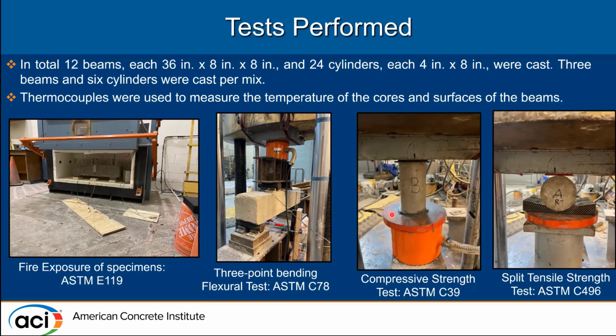Since we were to fire expose these specimens, we used thermocouples to study the surface temperature of the beams and cylinders. The tests performed on these specimens, starting with the slump flow test, that's ASTM C1611, and then the fire exposure of specimens as per ASTM E119, 3-point bending flexural test as per ASTM C78, compression strength as per ASTM C39, and split tensile strength as per ASTM C496.